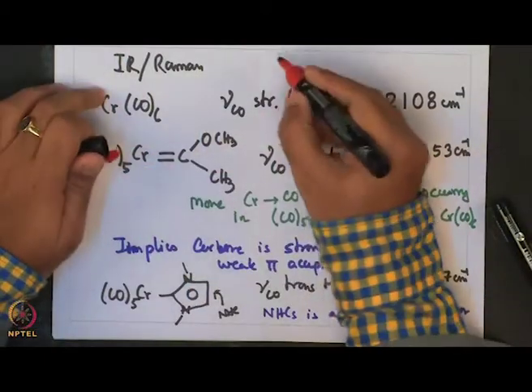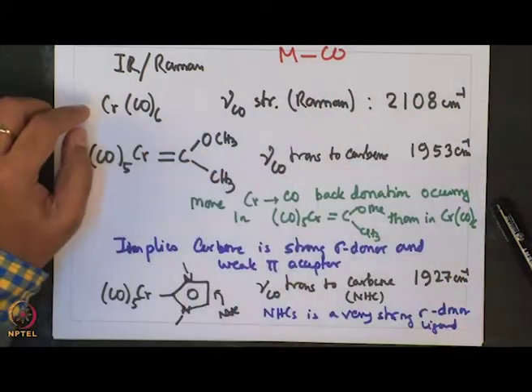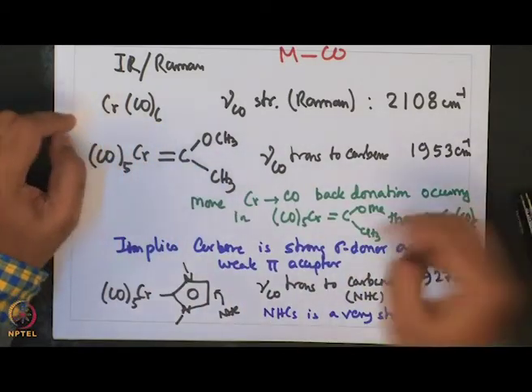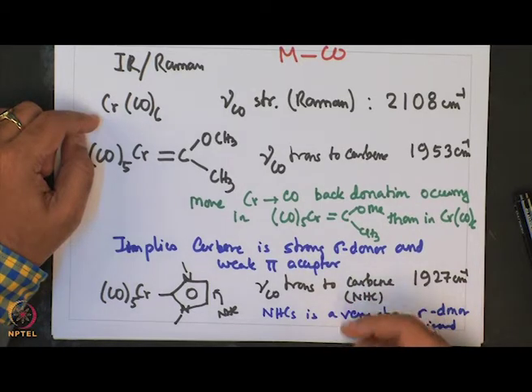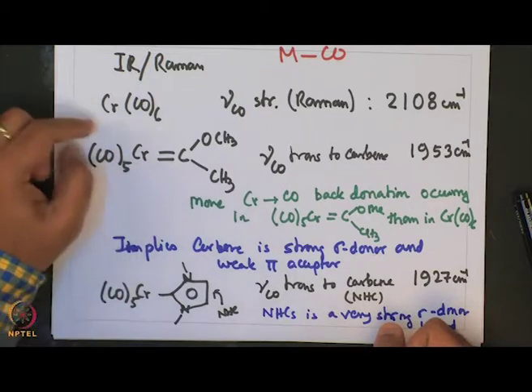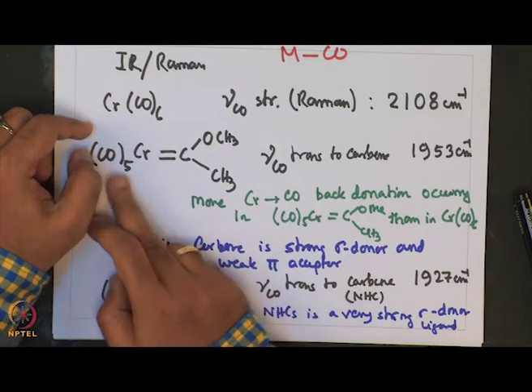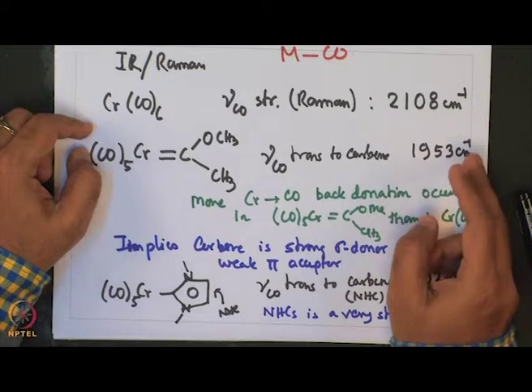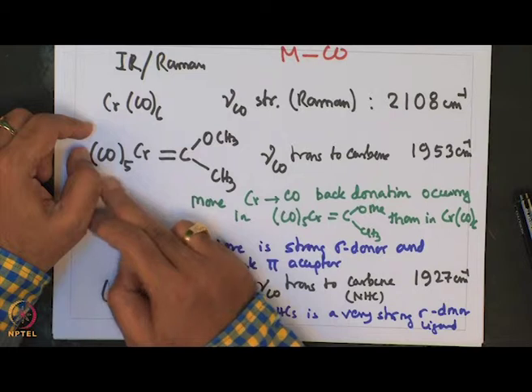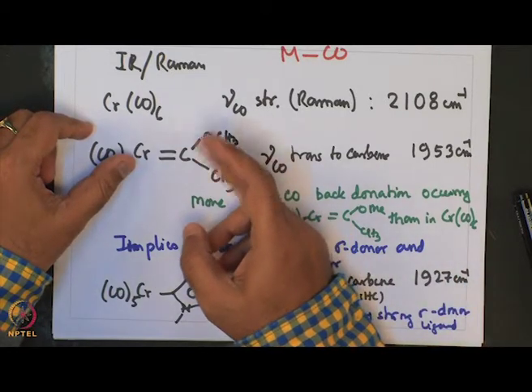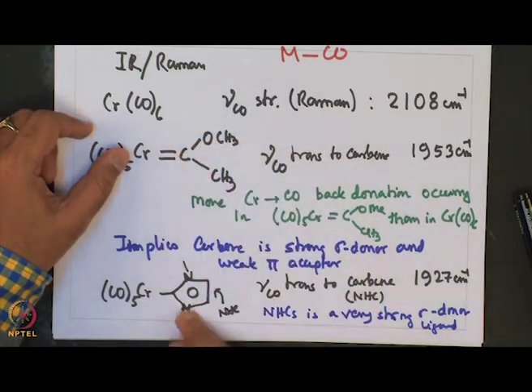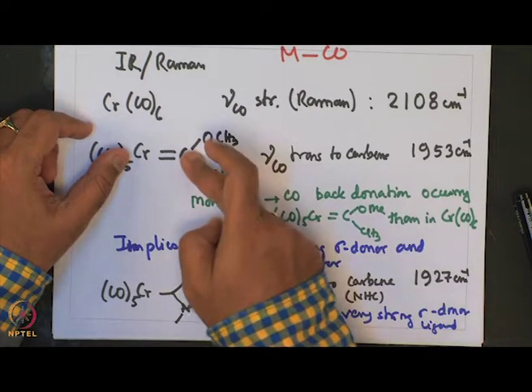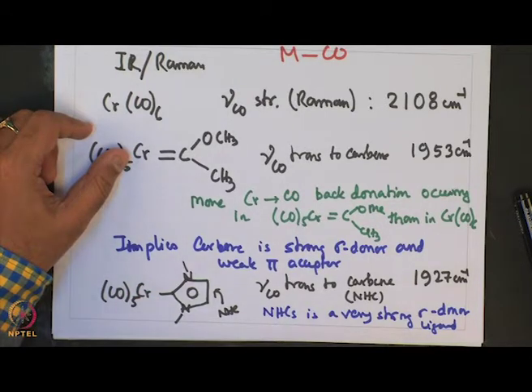So, what it shows is how the metal carbonyl frequencies shift as a result of this metal to carbonyl back donation that appears in complexes where carbene is a co-ligand along with metal carbonyls. For example, in this chromium Fischer carbene carbonyl complex, the carbonyl trans to carbene shows a stretching frequency at a much lower energy as a result of strong chromium to carbonyl interaction, which arises because of the electron donating nature of the carbene moiety. Now, as one goes from Fischer carbene to N-heterocyclic carbene, which is even more electron donating, the metal carbonyl interaction gets even stronger, resulting in a much lower nu CO stretching frequency at around 1927 centimeter inverse.